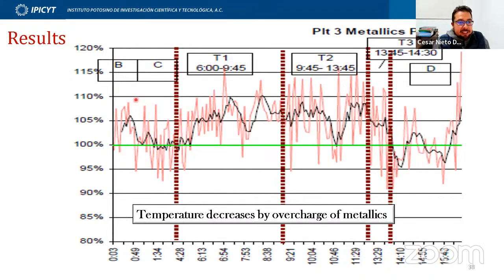This is actually the production line plot. Here the x-axis is time, and the y-axis is percentage, the percentage of the metallics, the scrap iron, that is loaded in the top of the furnace. And as you can see, this is the target. This is the amount of iron that you want to load in every charge. And you can see that at the beginning, this line, the charging, which is the black line, is very close to the green line.